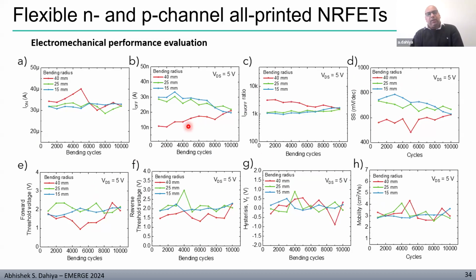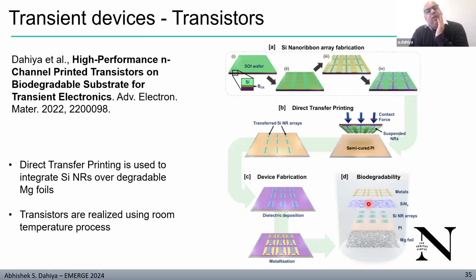So detailed characterization under mechanical bending we have performed and extracted the key performance parameters of transistors. I've not shown the transfer scan under bending, but these are the extracted parameters in terms of on-off ratio, which remains quite stable for up to 10,000 bending cycles at different bending radius. And SS value showed some change, might be because of the dielectric cracks or interface issues. Otherwise, mobility remains quite stable for these devices.